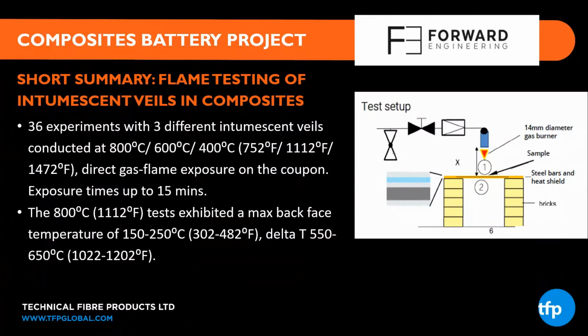So these experiments are really assessing the thermal insulation abilities of the Technofire veils to protect the backing laminate. Any damage or degradation of the laminate was also assessed. The test procedure can be seen in the diagram, with the Technofire-enabled laminate supported on a heat shield and 2 pillars. The gas flame directly impinges the front or top face, with the exposed face temperature being measured by thermocouple 1, and the back face temperature measured by thermocouple 2.